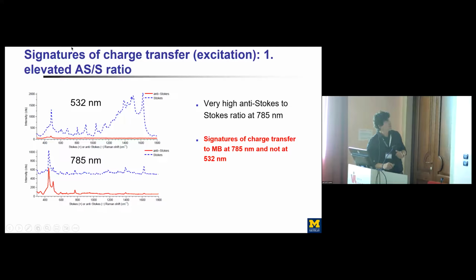So what we see here is that when we shine a laser of 532 on this metal and blue silver system, you see a very strong Stokes, meaning lots of molecules are vibrationally not excited, and you see a very weak anti-Stokes, meaning there's no heating of this molecule at 532 nanometers.